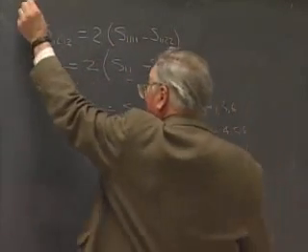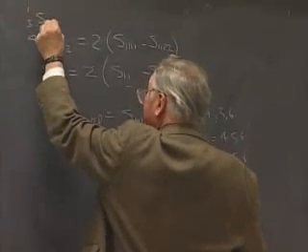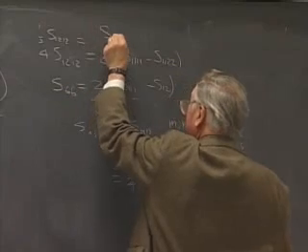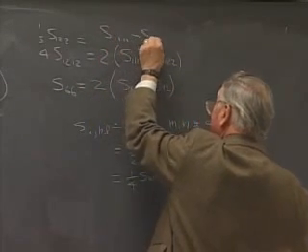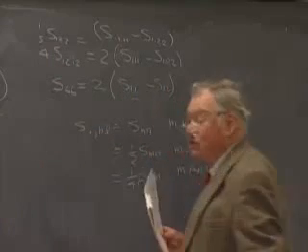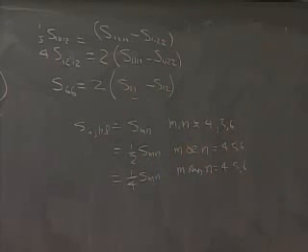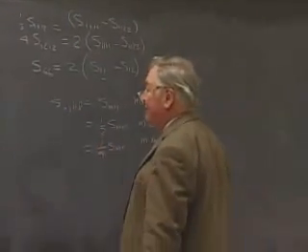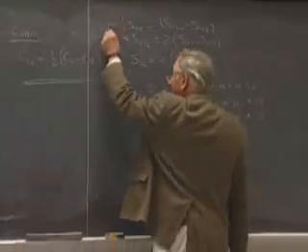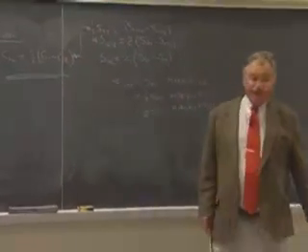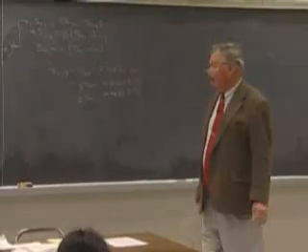And this says that 1/2 of S1212 is equal to S1111 minus S1122. So this is exactly the same constraint on tensor elements when we take out these factors of 2 and 4 that have been absorbed. So this, in fact, although it looks very different with those factors absorbed, is exactly this same relation. So the symmetry constraint is the same.